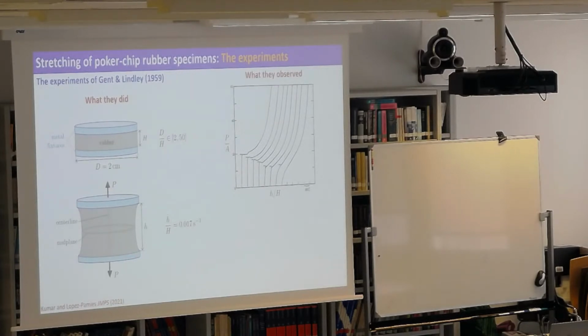They were measuring the force as a function of the applied displacement for a number of initial heights. And they always saw the same thing: the force was more or less linear, or stiff, if you like. Then there was a plateau, and there was a secondary stiffening. When they stopped the experiment after a while, they connected this plateau to the fact that cavities, as they call them, but they're actually cracks, appear within the bulk.